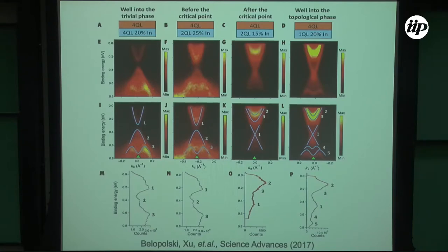There is no Dirac states there. But when we go there, we can. This is just the experiment I'm showing. Clearly, it's gapless. There is a Dirac state in there, right? So that means even though my top layer is just 4 quintuple layer bismuth selenide, I can now clearly see a multi-layer effect. So in other words, there must be a topological phase transition for me to see that. So this is my experimental diagnostic, how to design and how to fabricate and tune these multi-layers so that I can enter various topological states.